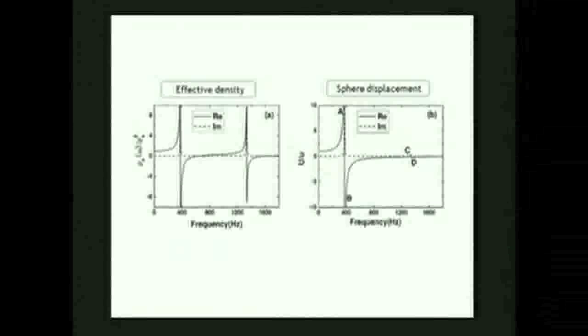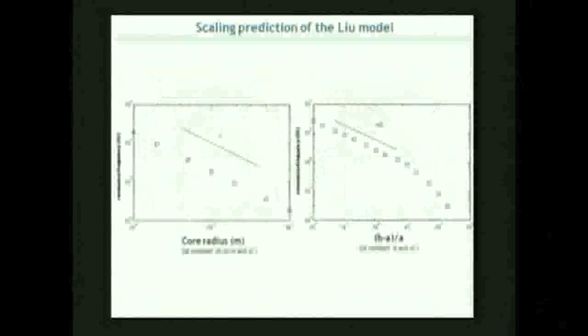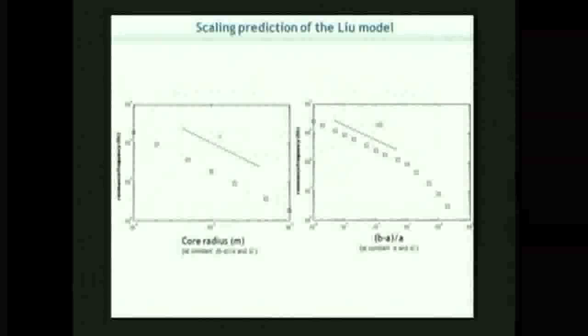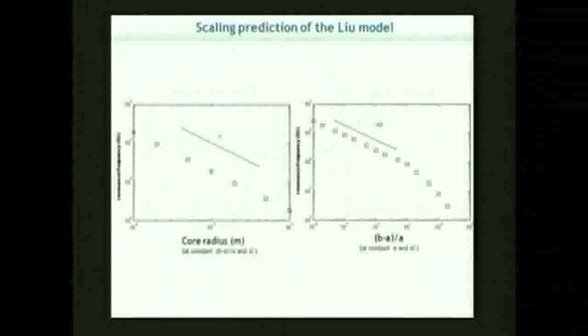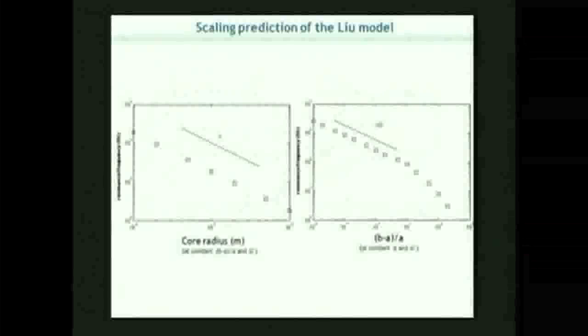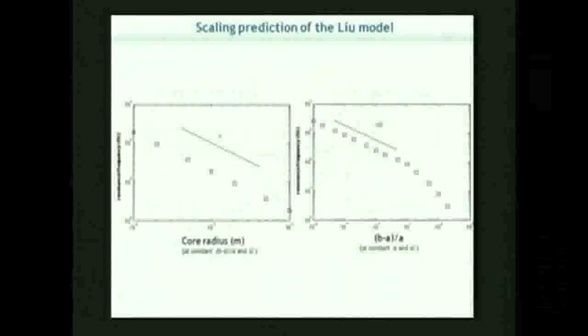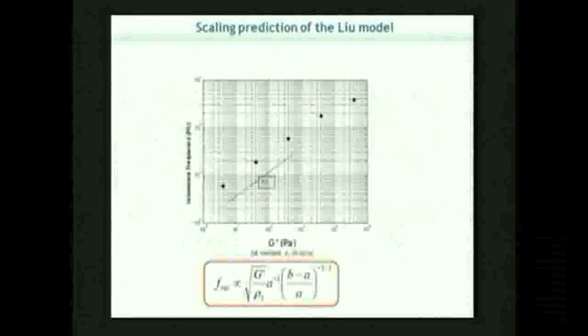Okay, so we have been able to calculate the resonance frequency as a function of the core radius and the resonance frequency as a function of the ratio of the shell divided by the core radius. And you see that the larger the core radius, the smaller the resonance frequency. And it's the same for the thickness of the shell.